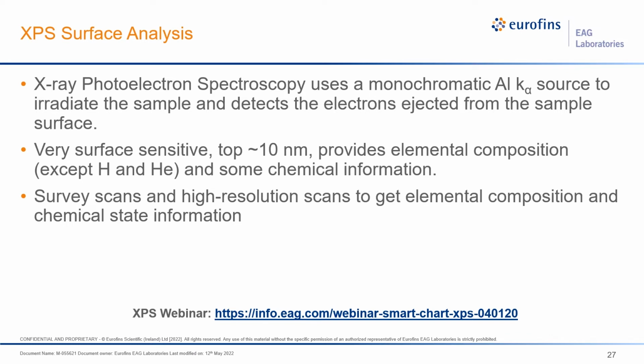Thank you, Yannicka. So I'm going to go through the XPS surface analysis right now. The XPS tool we use has a monochromatic aluminum K alpha source to radiate the sample, and we look at the electrons that come off the surface. It's very surface sensitive, so as opposed to the IR, which looks moderately deeply into the sample, we're looking just at the very surface to get the elemental composition, except for hydrogen and helium, which we can't see. And in the high-res scans, we can get some chemical information. So we did both survey scans and high-resolution scans to get the elemental composition and the chemical state information. And down below, there is a separate webinar that we've done in the past on XPS, and that's the link to it if you want to watch that webinar.